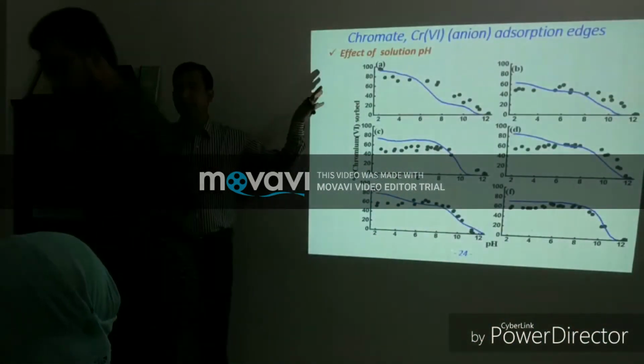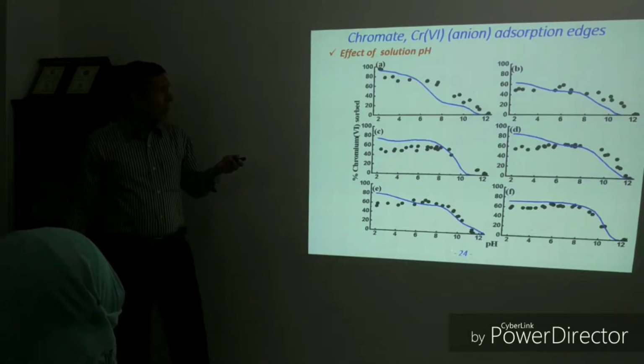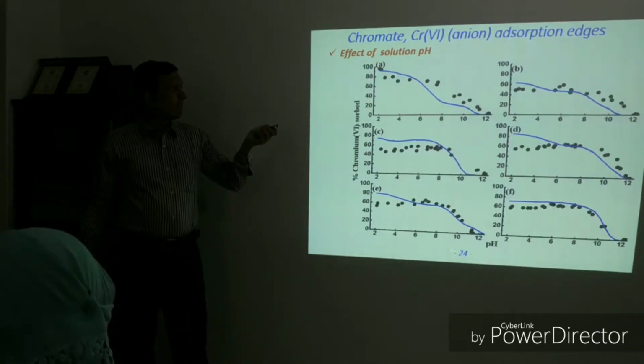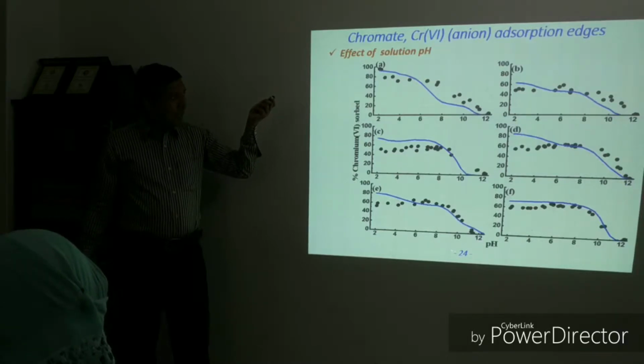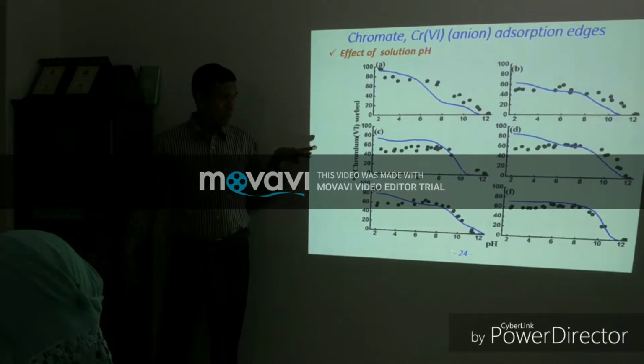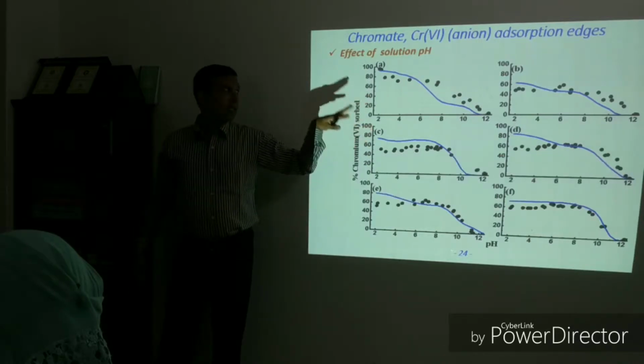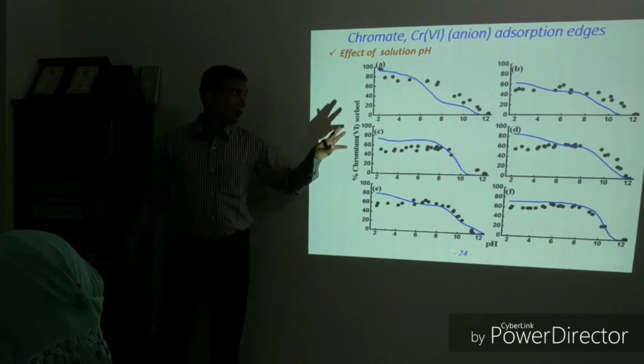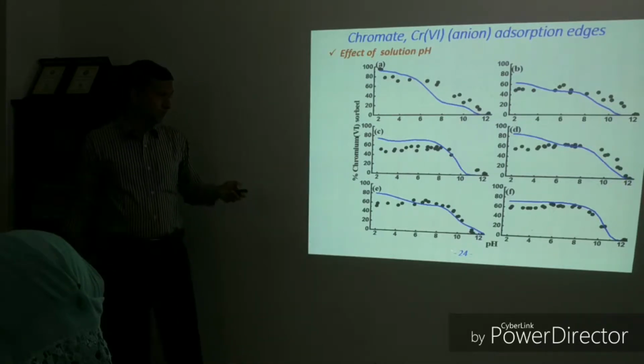Then we have studied chromate adsorption phases, and here is the effect of solution pH. In case of birnessite, we can see that the amount of chromium adsorbed decreases with increasing solution pH. In the other cases, adsorption first slightly increases, reaches a maximum, then decreases. This primarily occurs due to surface properties.